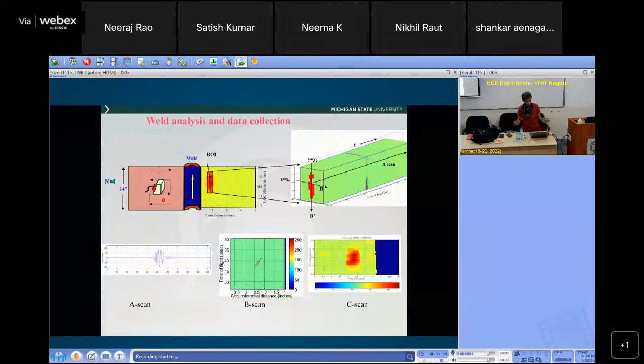Okay, so in ultrasound, there are 3 modalities of looking at the data. This is called the A-scan. You just put a transducer in one location and look at the time. This is the time axis, and you're looking at the return amplitude. And this is called the B-scan, where you move it along one line, and at each point you plot the A-scan, and when all the A-scans are plotted together, you get this image of the crack. That's what medical ultrasound does. Instead of moving one transducer, you have an array of transducers, and then you get this whole B image. And if you can do a full raster scan and plot the max peak value at each point, you get what's called a C-scan. So you have A, B, and C-scan modalities for looking at an image.